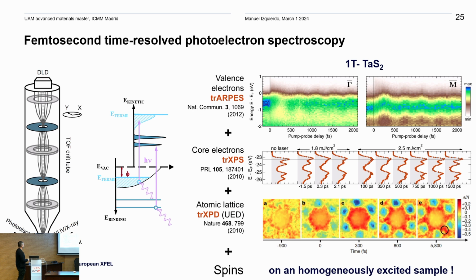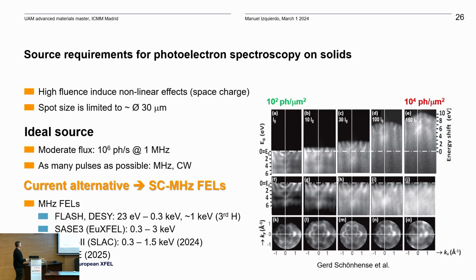So photoemission is an ideal tool because you can study both the surface and the bulk properties of your material. What we want, as I said, is to realize the ultimate dream of measuring all the properties of your system in one experiment. You have to note here that this experiment of the atomic structure was not obtained with time-resolved photoelectron diffraction, because we have not been able to do this yet in forward scattering. So this was done with electron diffraction.